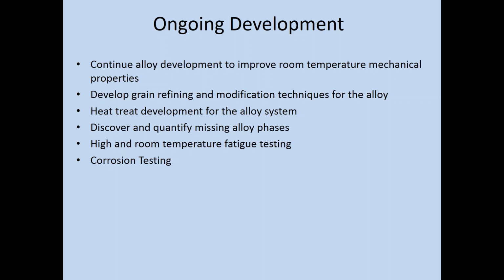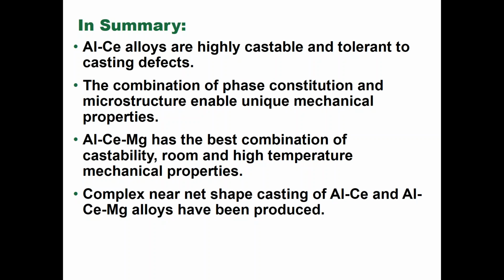We're doing high and room temperature fatigue testing as well as corrosion testing. Although Oak Ridge did some preliminary corrosion testing and it was very, very favorable, so we don't anticipate any problems there. So in summary, these alloys are highly castable, tolerant to casting defects. If you cast any of the binary alloys, the alloys that contain magnesium, you would say that they cast just like 356 does. The combination of phase constitution and microstructure enables unique mechanical properties, certainly at high temperatures.